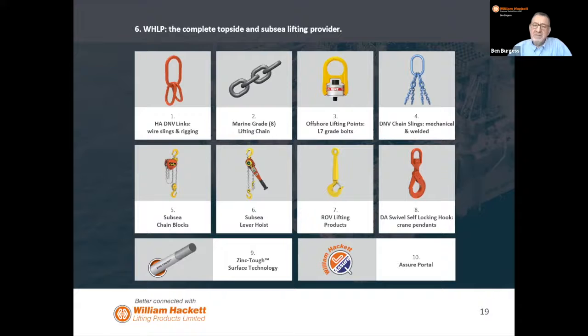But the chain used has a maximum hardness of 38 Rockwell C, and it also comes with a zinc tough finish that delays the onset of corrosion. It also has non-spark attributes, and its major strength is its toughness and ductility.